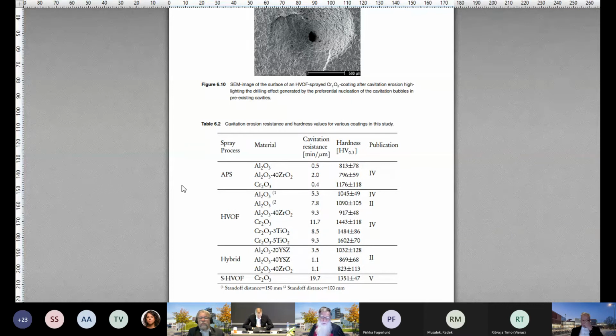Please remind me of the number of hardness tests that you did to get those standard deviations. 10 tests. And why did you choose 10? On what basis did you choose 10? Sorry? By convention. It's been kind of a standardized test to do 10 repetitions. Now, I know standard deviation from 10, it's a bit of a stretch still, but it's better than 5, for example. But 20 is better than 10 as well. And 30 is even better.